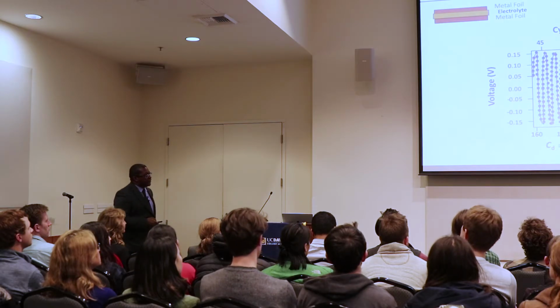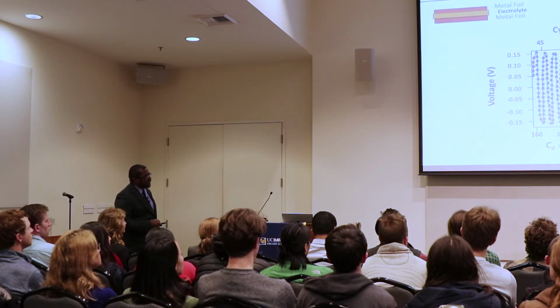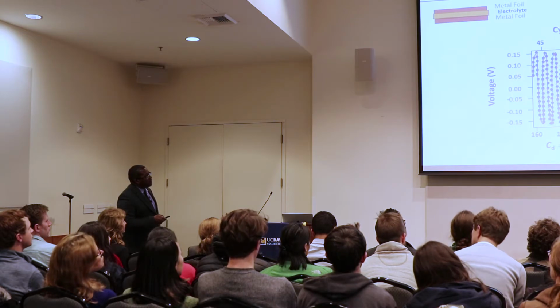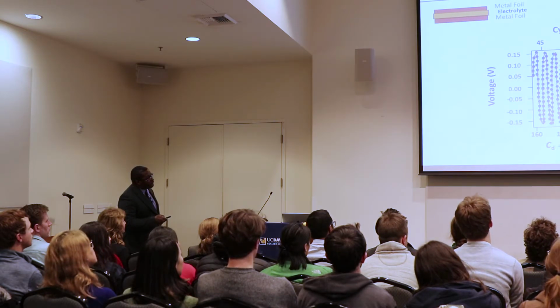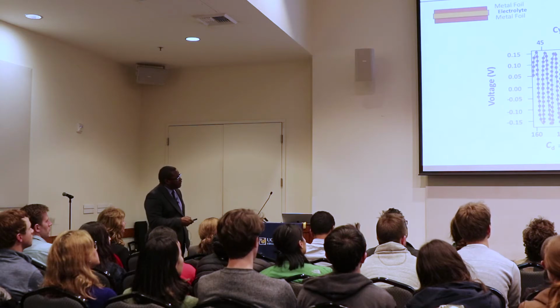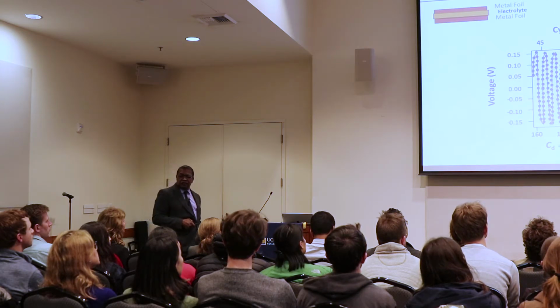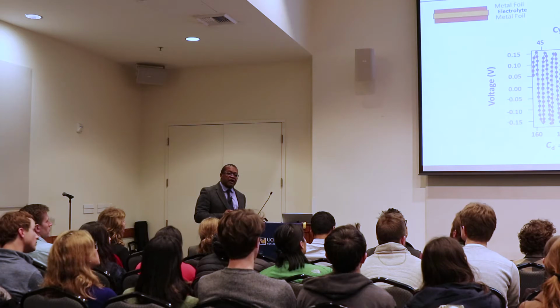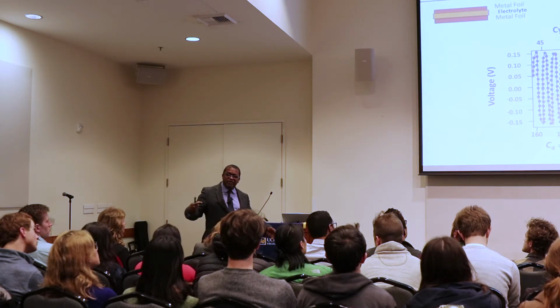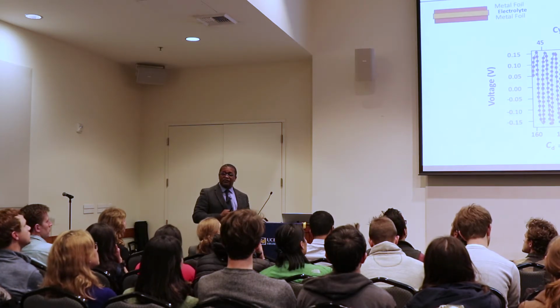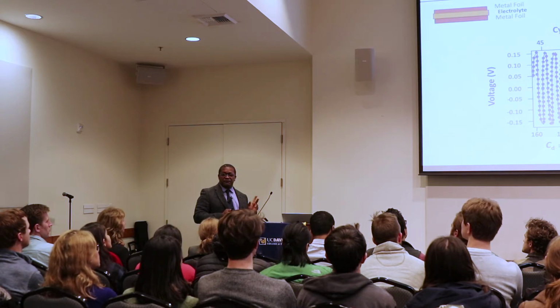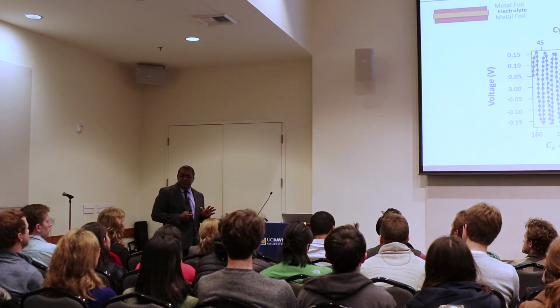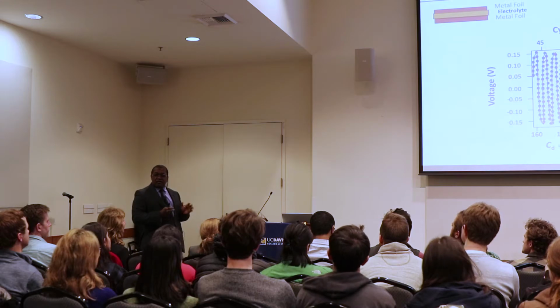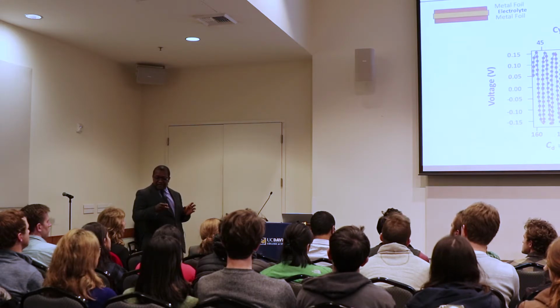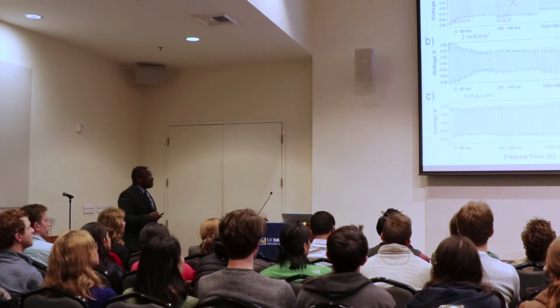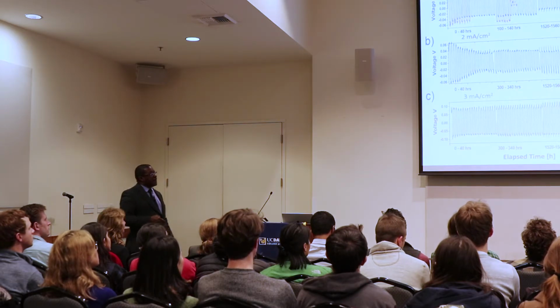What they discovered is that very quickly, in this example, after roughly the 50th or 52nd cycle, there's a sudden drop in the voltage. And when they opened the cell, unsurprisingly, the dendrites had crossed and shorted the cell, which means the resistance has dropped.